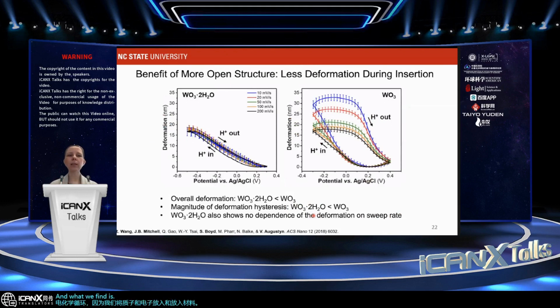And what we find is that in agreement with the structural transitions that were showing these phase transformations happening when there was no water, this more open structure that would contain water, that had a layered structure, had less deformation overall during ion insertion with less hysteresis. So the mechanics was really tracking, the electrode deformation, I should say, was really tracking with our electrochemical current measurement.